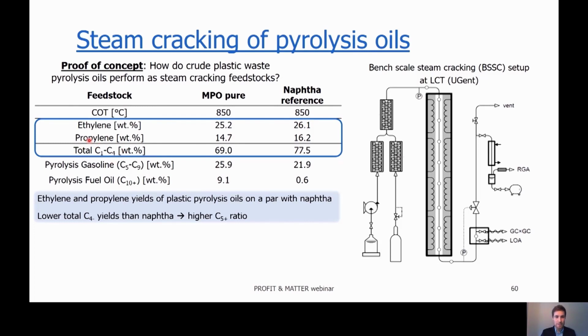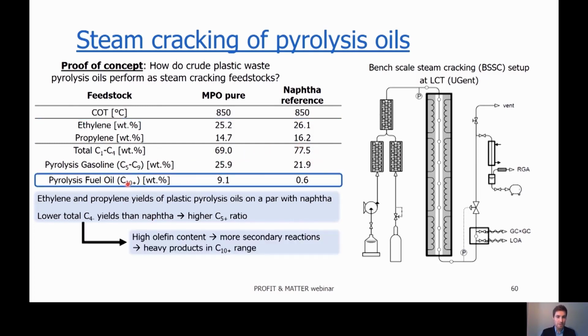However, it can be seen here that the total C4-minus, total light products, are a bit lower than for the naphtha reference. That means we are getting more heavy products, which can be seen here in the pyrolysis fuel oil range, C10+. We reach almost 9% of these products with our MPO pure, while we get less than 1% with the naphtha reference.